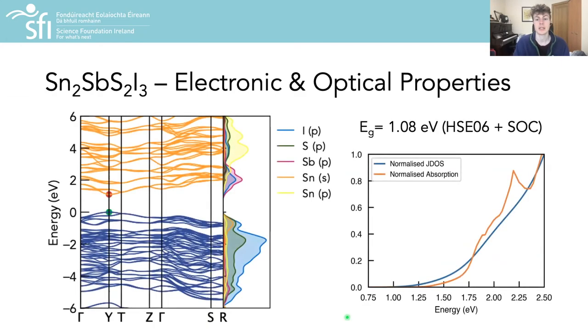We also calculated the electronic structure using hybrid density functional theory, including spin-orbit coupling effects, to find a direct gap of 1.08 electron volts, which is ideal for photovoltaic operation, with a VBM composed of anion P states and a contribution from the tin 5s² states, and a CBM arising from iodine P and antimony P states.